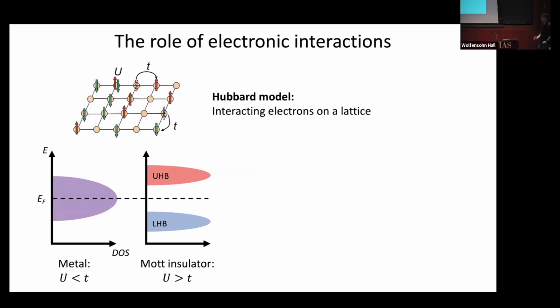In fact, the most interesting cases are where this naive understanding breaks down, and that often is associated with the role of interactions among electrons. One celebrated example is the Hubbard model, where you can think of the simplest possible interacting system. You have a lattice of sites that the electrons can occupy, and there are two parameters that characterize this Hubbard model. One of them is the likelihood that an electron can hop from one site to an adjacent site. That's characterized by a parameter T. The other parameter is that if two electrons try to sit at the same site, there's some Coulomb repulsion. There's some on-site local energy U that disfavors that sort of interaction.